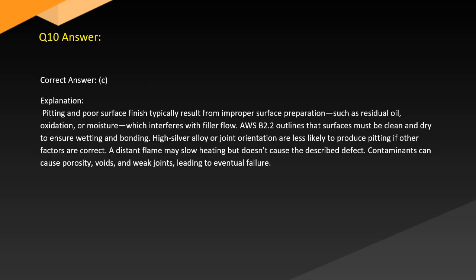Answer. Correct answer: C. Explanation: Pitting and poor surface finish typically result from improper surface preparation, such as residual oil, oxidation, or moisture, which interferes with filler flow. AWS B2.2 outlines that surfaces must be clean and dry to ensure wetting and bonding. High silver alloy or joint orientation are less likely to produce pitting if other factors are correct. A distant flame may slow heating but doesn't cause the described defect. Contaminants can cause porosity, voids, and weak joints, leading to eventual failure.